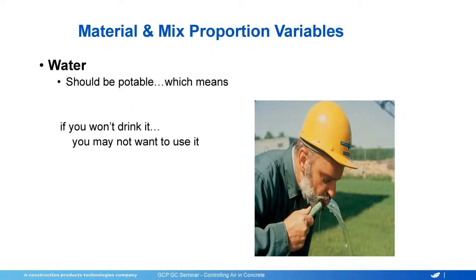Okay, water needs to be potable, which means, if you don't drink it, you may not want to use it. There are a lot of producers that use recycled water, wash water, those kind of things. We actually have some producers that are drawing water out of a canal, and they can do that successfully as long as it's consistent. Now, if you're collecting water in your plant and you've got oils and stuff running off into the water, that can wreak havoc one way or the other with your air entrainment. So again, like all the other ingredients that we're talking about, being consistent with the water is the key, and not just the makeup of the water, the composition of the water, but how much water I'm using in the mix.